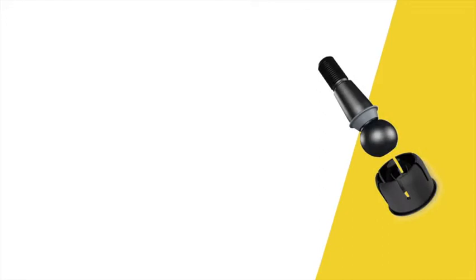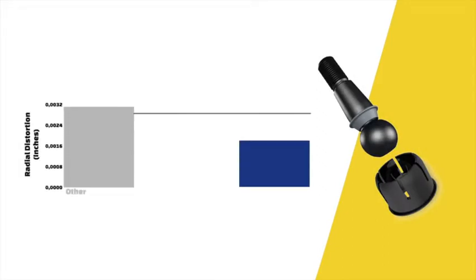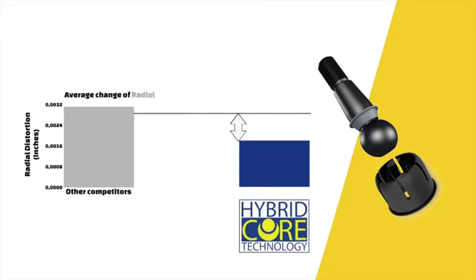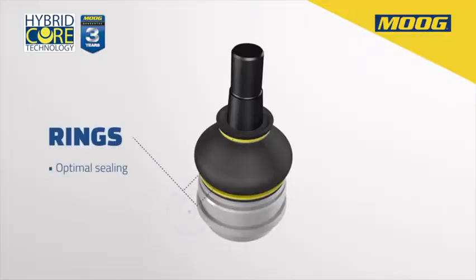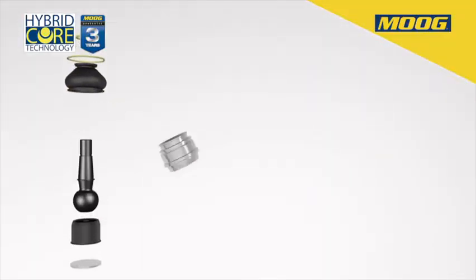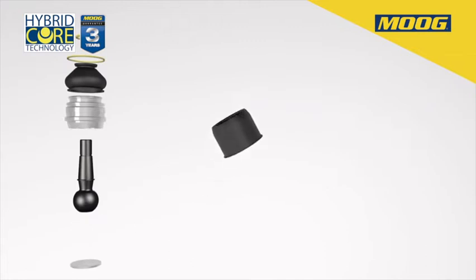Thanks to MOOG's hybrid core technology, the induction heated studs mounted in the new carbon fiber reinforced Teflon bearings offer up to 40% reduction in radial deflection, which is the measured variation in the diameter of the pin's ball caused by the stresses to which the metal is subjected during normal use. The quality of this bearing is key for the correct operation of the spherical bearing.